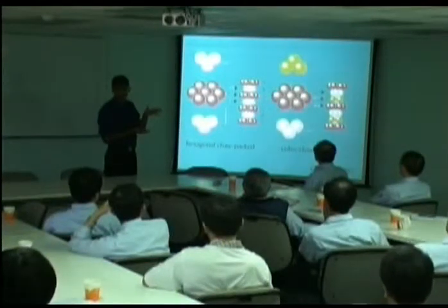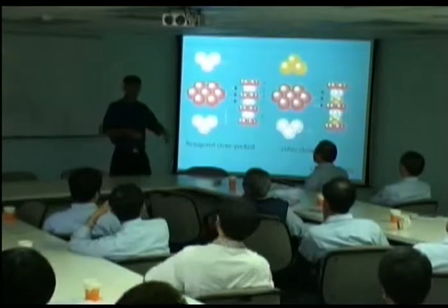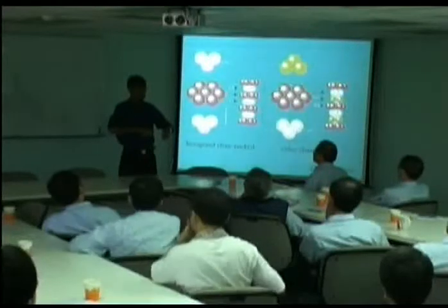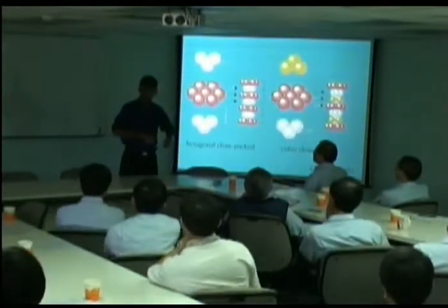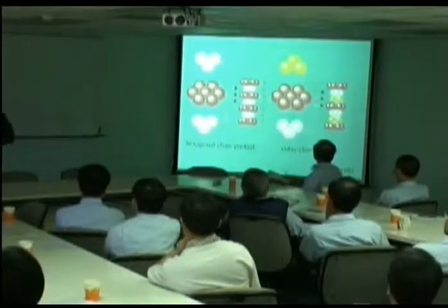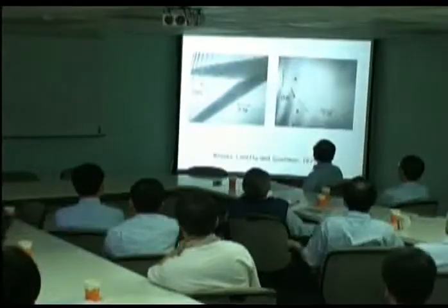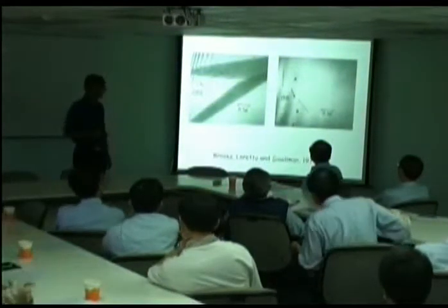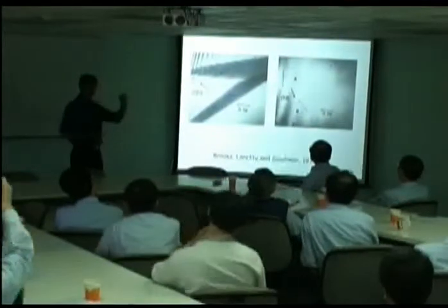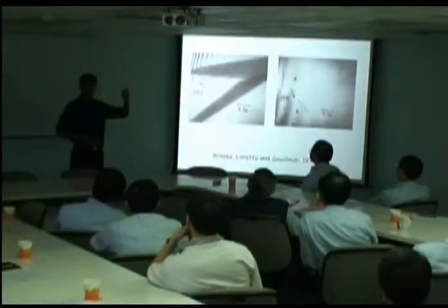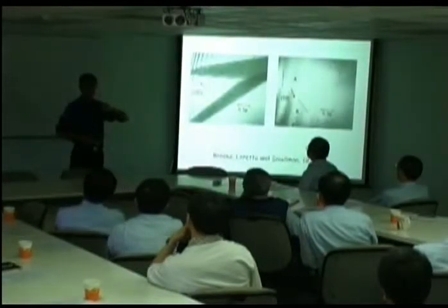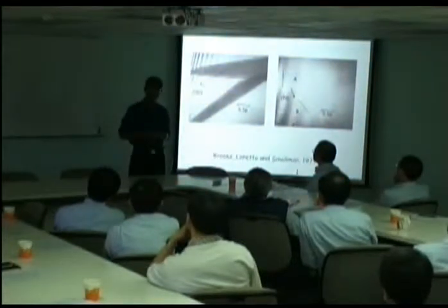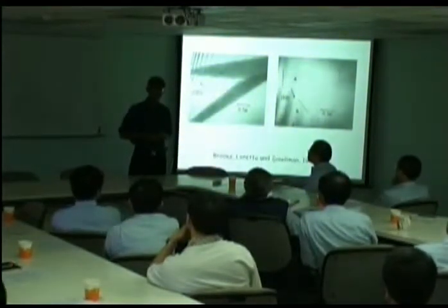Okay. And that, of course, is the stacking fault that you see in austenite. When you see a stacking fault, the local sequence has changed from A, B, C, A, B, C to A, B, A, B. So these are stacking faults in austenite, and this is work done in 1979. And here, locally, we have what we think is hexagonal close-packed iron. Now, how do we prove that this is really a nucleus of hexagonal close-packed iron?